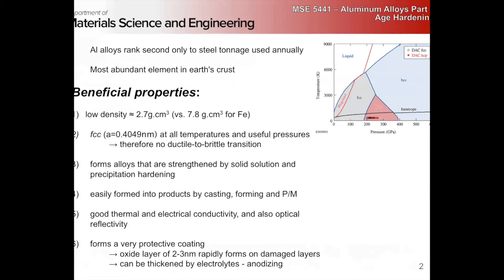It's the easiest, because we only have to think about one slip system. We never have to worry about twinning, right? We don't have to worry about martensitic transformations. And we can focus on precipitation effects and solid solution effects. Then once we have that down, we can go to steel, where we add allotropes and other phase transformations into the mix, right?